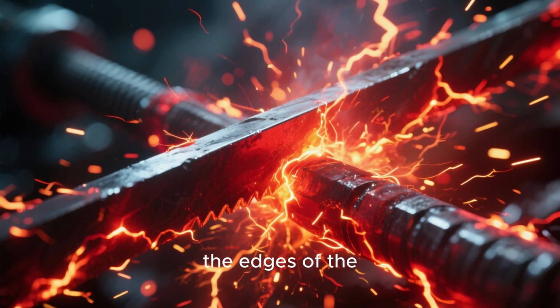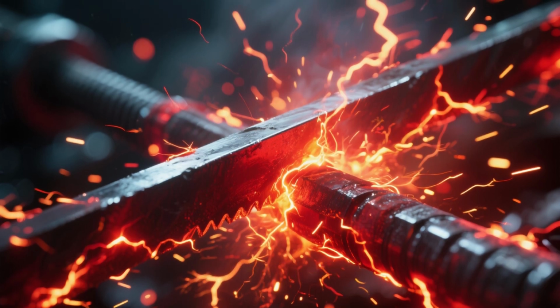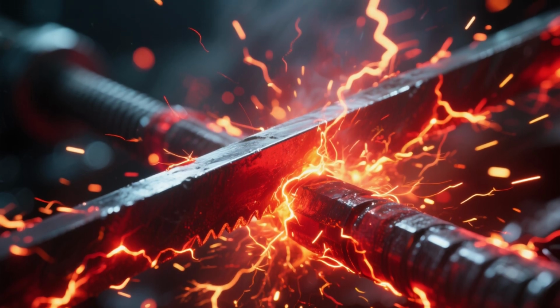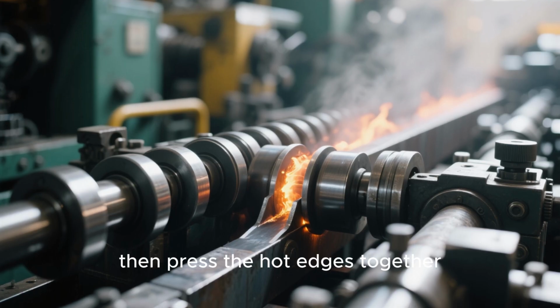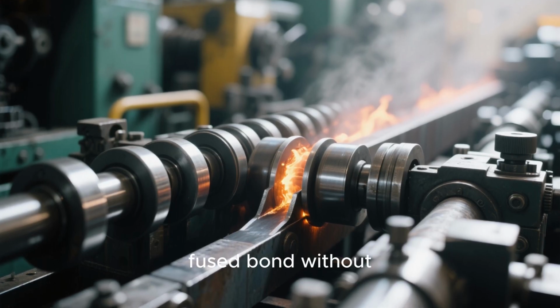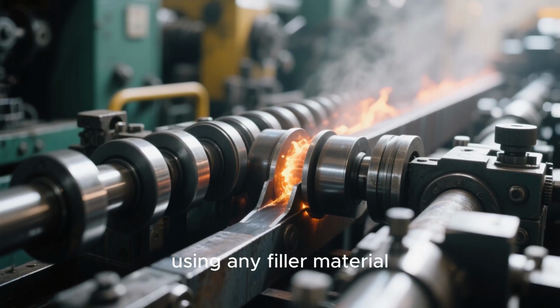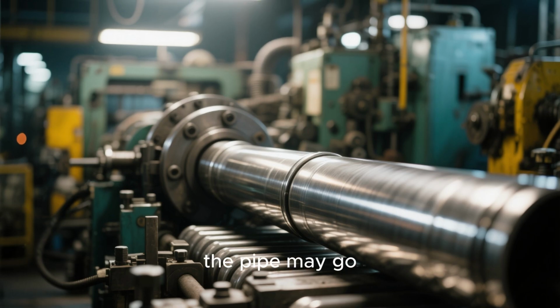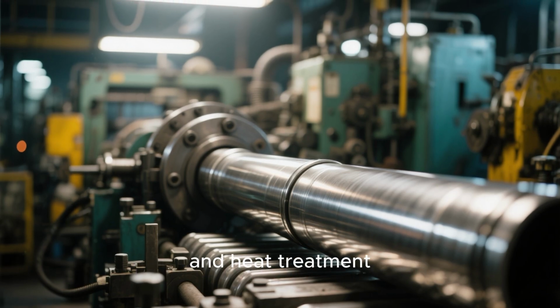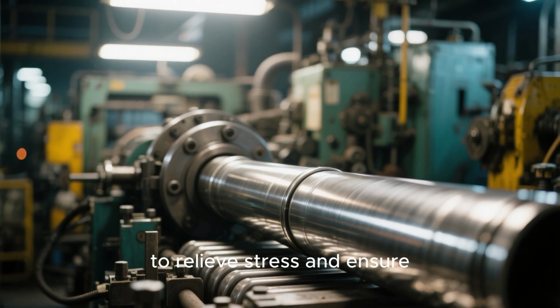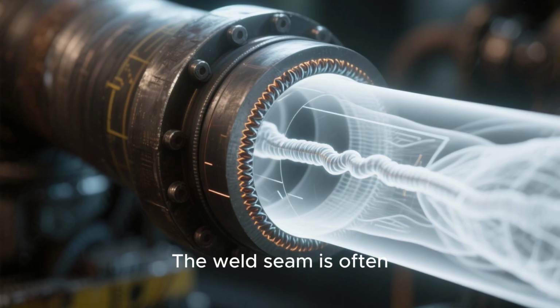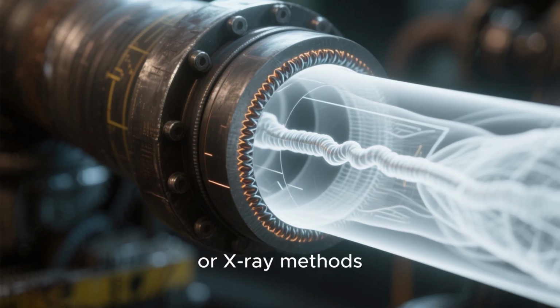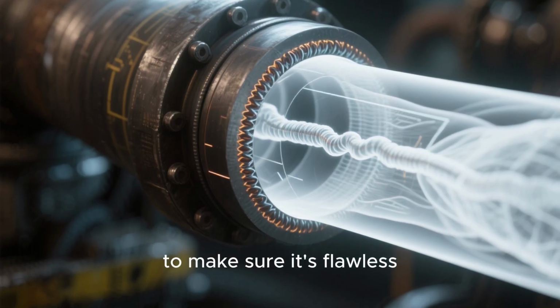High-frequency electrical current is passed through the edges of the steel, heating them to a forging temperature. Mechanical rollers then press the hot edges together, creating a strong fused bond without using any filler material. After welding, the pipe may go through additional sizing rollers and heat treatment to relieve stress and ensure uniformity. The weld seam is often tested using ultrasonic or X-ray methods to make sure it's flawless.